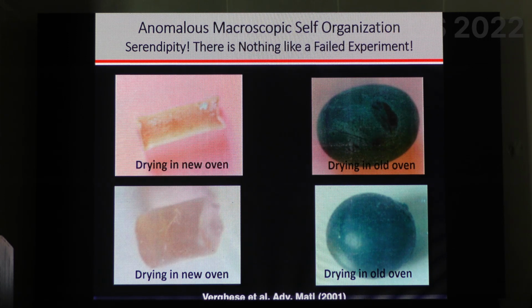She put her gels in the old oven, and she was very careful, she was very observant, and what she felt was, as she closed the door of the oven, some rust fell on this polymer. And from the rust, transition metal ions diffused into the polymer, and the polymer, what she put in was this piece of cylindrical hydrogel, and slowly overnight it transformed into that, right? And she thought this was very exciting.